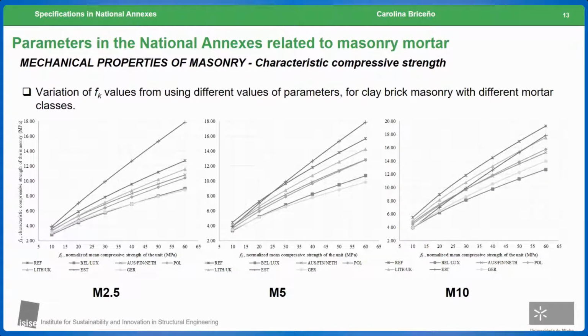Here, I would like to show the compressive strength of the masonry in terms of the compressive strength of the unit. We see that the patterns are slightly the same. Only in this case, there are 3 graphs depending on the mortar class that is chosen. We see that in the case of mortar class 2.5 and 5, the highest and the lowest values of the compressive strength of the masonry, determined using the expressions available in the British and the Polish national annexes, are the ones with the highest and the lowest value correspondingly. But in the case of mortar class 10, the highest values are the ones obtained considering the expression available in the standard, and the lowest are the ones considering the expression available in the national annex of Belgium and Luxembourg.